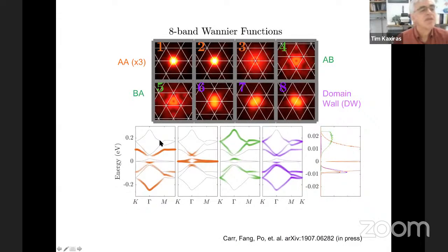So here is now the best model that we can produce, consisting of 8 bands. The bands labeled 1, 2, and 3 are centered at the AA regions. This answers the question that was raised in the previous talk: where are these electronic wave functions? Here they are. Bands 1, 2, and 3 are centered at the AA regions. Bands 4 and 5 are centered in the AB or BA regions. And the bands 6, 7, and 8 are centered at the domain walls. So these 8 bands together produce a very reasonable representation of the ab initio bands. And you see that you need all of them because they are very strongly coupled.